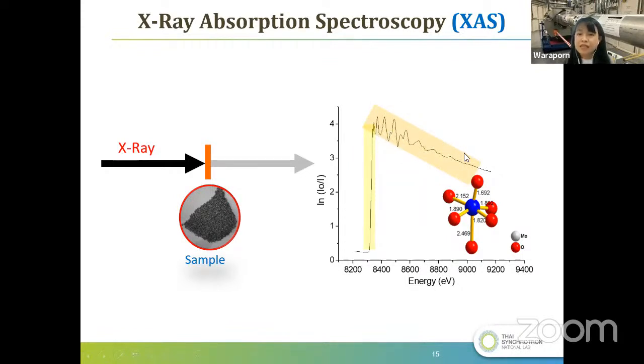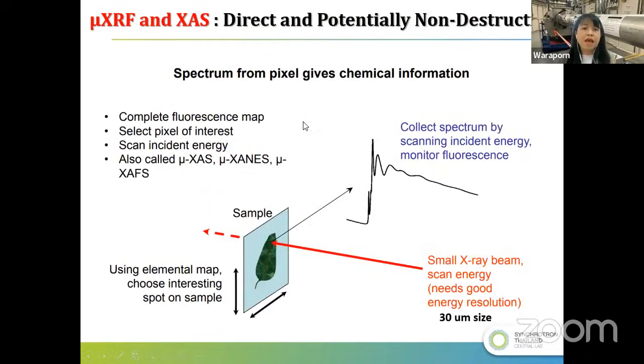And for the peaks here, you can get information on the neighboring elements. Like for this one, suppose molybdenum is in the core, what is the bond length of the molybdenum to the neighboring oxygen atoms, and how many oxygens bind to your sample like this. So it's a very useful technique. And you can combine X-ray fluorescence with X-ray absorption. You can get the result of element content and oxidation state of your sample at the same time.